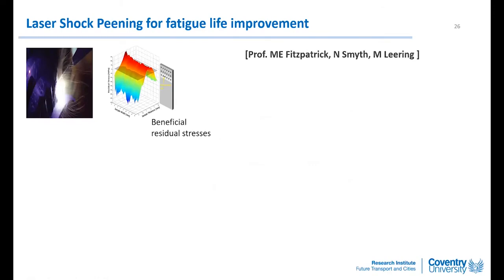So to conclude my metal fatigue lecture, I just want to mention laser shock peening for life improvement. This is not my work. This is the work by Professor Mike Fitzpatrick, Dr. Niall Smyth, and the PhD student Mitchell Leering at Coventry University. I have never done this, but I think this should be included in the modern technologies for design against fatigue. What they did was use a laser to introduce a beneficial residual stress, and that is in compression. This was the X-ray synchrotron measurement of residual stress on the wing panel, on the aluminum panel.